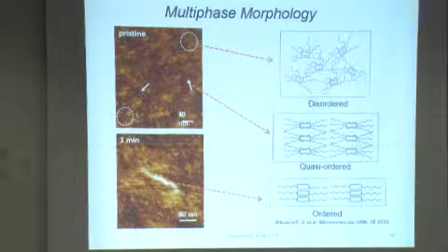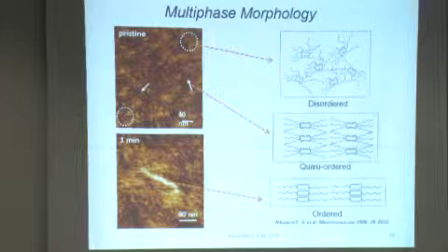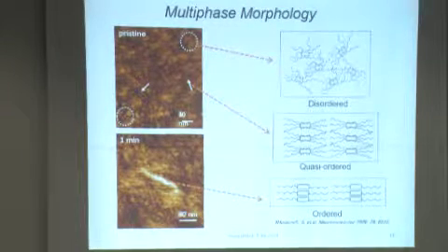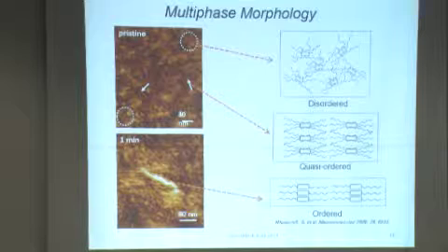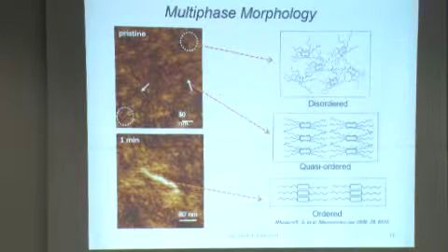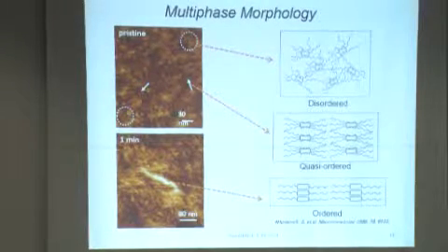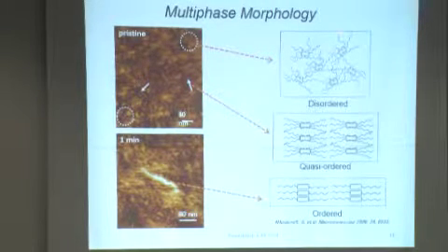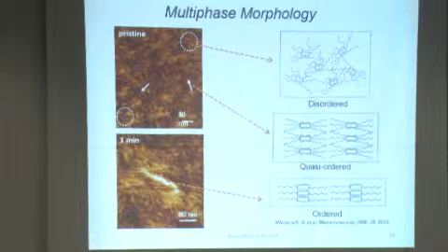All right, so we looked at this a little bit further, and during that sonication process, it appeared that what we were seeing was a transition from a material that appeared to be largely disordered into one that had phases that were disordered, coupled with phases that were highly ordered, and then ones that appeared to be quasi-ordered. And then going back to the literature, we found a paper by Stephen Holdcroft at SFU, Simon Fraser University in Canada, where he had postulated that P3HT in solid films has a blended morphology composed of these three particular phases.